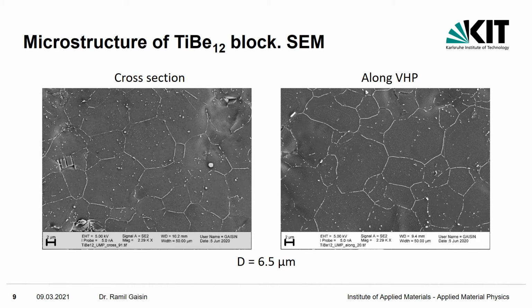Let's take a look at the microstructure. It consists of equiaxed grains. There are some particles within grains and at grain boundaries. There are no visible differences in the microstructure along and across the pressing direction. The mean grain size is measured as 6.5 microns.